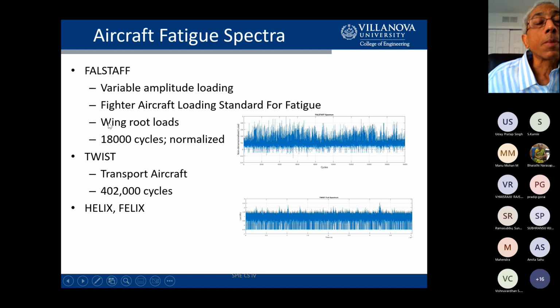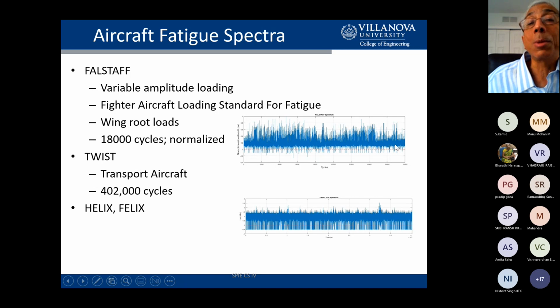And basically, it's been compiled over about 300 or 400 flights of a fighter aircraft, and there's 18,000 cycles. A cycle is basically an increase in load followed by a decrease in load. And so those 18,000 cycles are shown in this graph. And obviously, if you want to put 18,000 cycles inside a small rectangle, then it's going to look pretty crowded. And that's what you're seeing over here. So the cycles are along the x-axis, and the non-dimensionalized loading amplitude is shown on the y-axis. And so it's a very busy pattern.